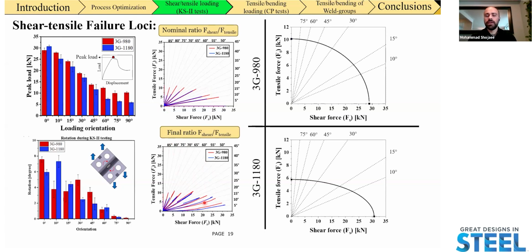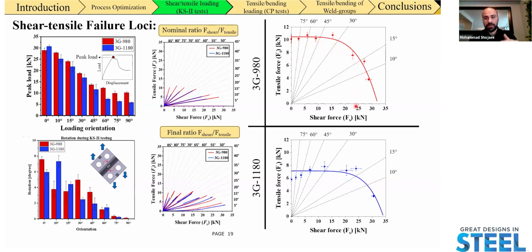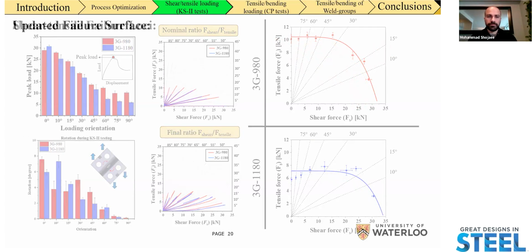Now, by having these data points, we can reconstruct the failure loci in the shear-tensile loading conditions as compared to what we had initially. So initially, we just have lap shear and cross tension data points. Those would be the two black dots here. But we can add the nominal loading ratio that we got from the KS2 test in all the intermediate loading orientations. This is still the nominal one, which is following the nominal dashed loading orientation, but we can update it by the actual final ratio of the shear load and the tensile load being applied to the spot weld, so we can see how that initial failure loci is expanding and giving us a more accurate representative failure loci that can be implemented in our models.